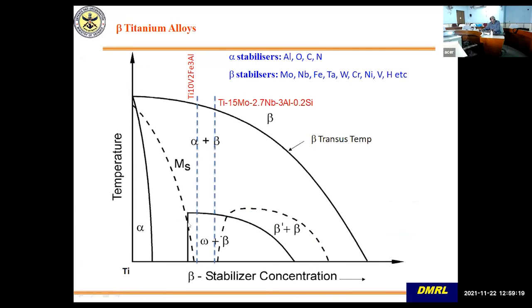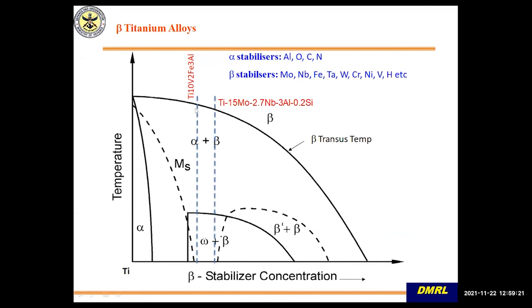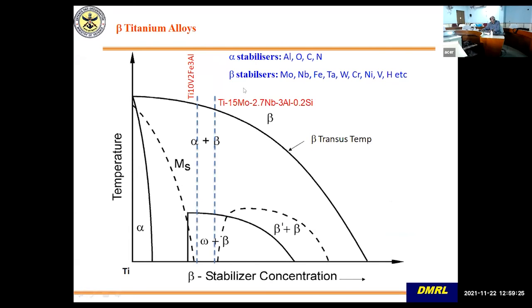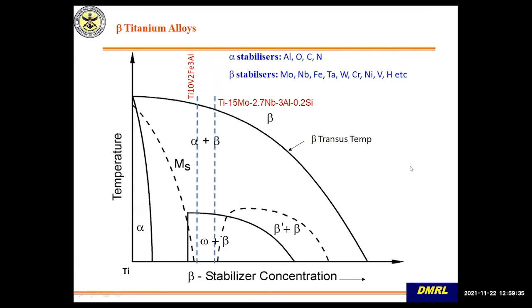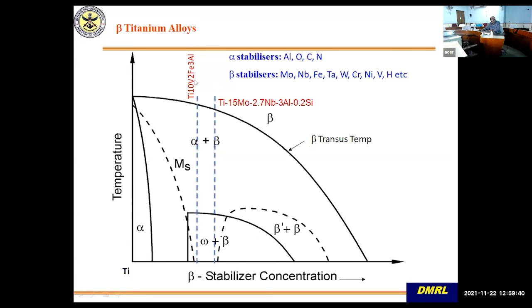I will give you examples from 10-2-3 and another alloy, beta 21s, which are located just beyond the martensitic formation line here. These have sufficient beta. This alloy has 10 vanadium, 2 iron, so you can see a lot of beta content in this. Also, you can see a lot of beta stabilizers such as molybdenum as well as niobium.